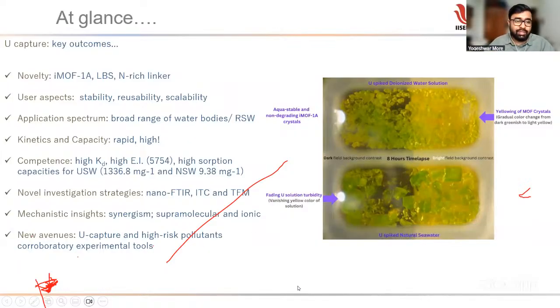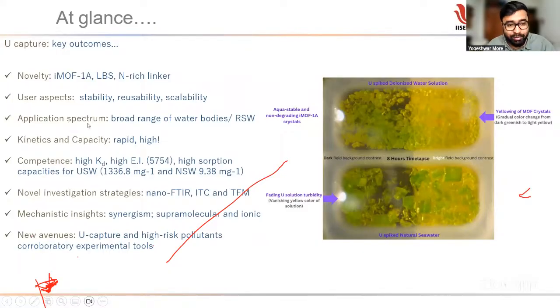So far, what we achieved in this case is the novelty. We have prepared an ionic assembly, that is IMOF-1A, which is enriched with Lewis basic sites in the form of pyridinic nitrogen, derived from the linker. Second is the stability and reusability aspect, and third is the scalability. You can see the MOF has been scaled up to grams. And the application spectrum: what is this? It can work in a broad range of water bodies. It doesn't only work in modeled seawater, lake water or potable water; it can be deployed in real-time seawater.